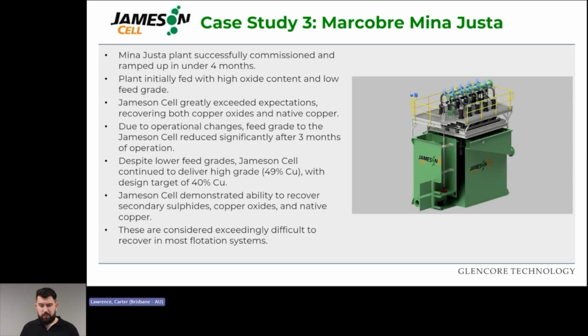Now, the plant was initially fed with a high oxide content, low feed grade, and the Jameson cell greatly exceeded the expectations because it was recovering both the copper oxides and the native copper. Now, due to the operational changes, as mentioned, the feed grade to the Jameson cell reduced quite significantly after 3 months. Despite these lower feed grades, the Jameson cell still delivered high grades at high recovery above the design case.